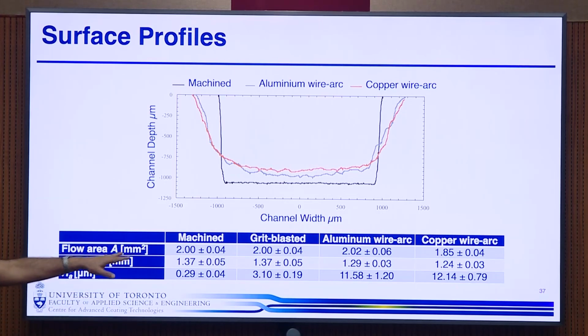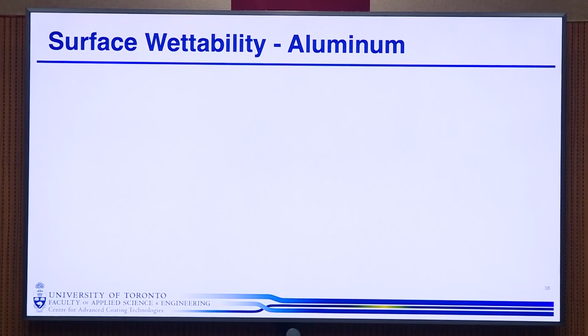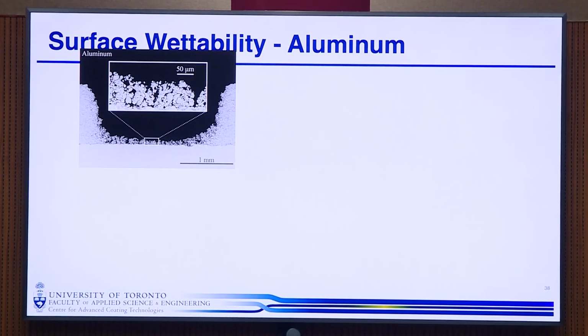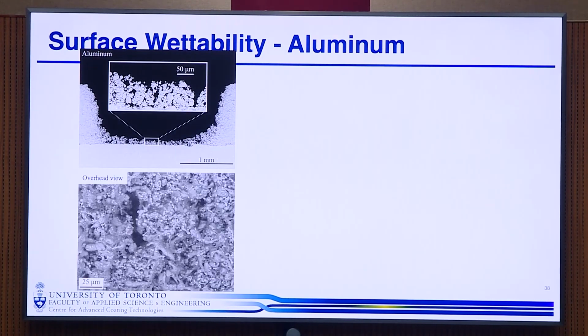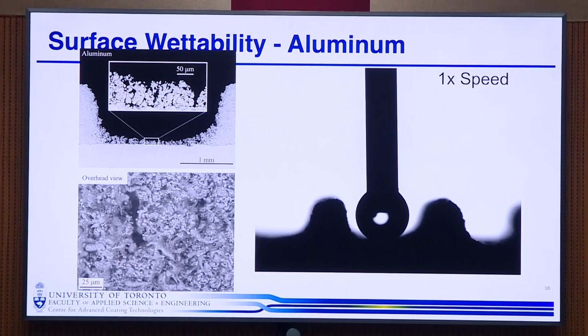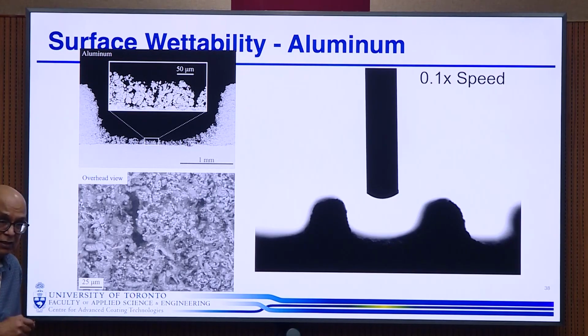We have a roughness of about 12 microns over there. Okay, so if you look at the surface wettability, this is the aluminum one. And if you look at it from the top, this is sort of what the structure looks like. And you put a water droplet on that, and it just soaks right in. So this is a very hydrophilic surface.